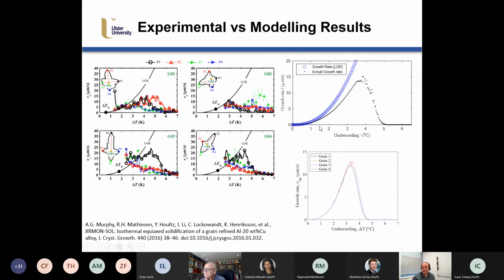So if you see here, these are the 4 grains. And these are the back calculated growth rates for all of these grains at different locations, and we're getting around 13 micrometers per second, and that's not so far off from the average growth rates when you combine each individual crystal. You know, the average growth rate in the 4 directions, it would be quite close, I would imagine.